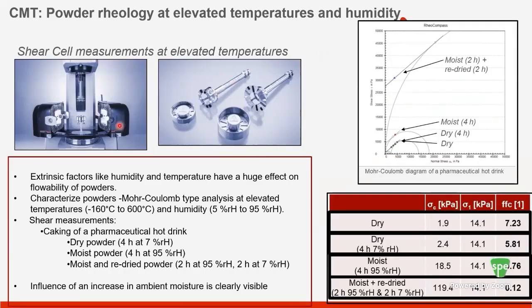This slide hopefully shows you the incorporation of a ring shear cell to understand quasi-static properties of powders on a single drive rheometer. Here, you can put your powder, and there's a convection oven where you can apply different temperatures and even humidity conditions. Typically, there are no devices out there which can characterize such things, so this is very unique. It opens up really new experimentation.